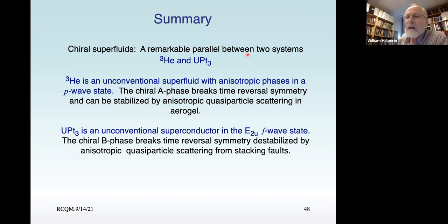Well, that best comes from the characterization of the anisotropy itself. The way we do that is using optical birefringence, because you can shine light on this thing and measure with fairly high precision how much anisotropy is there. If you don't apply stress, in other words you don't have strain, then there's absolutely no birefringence.